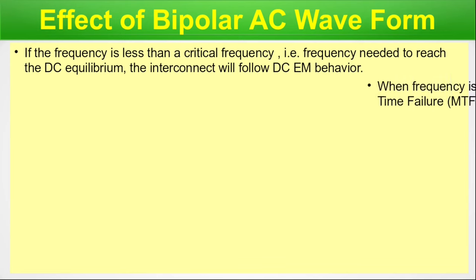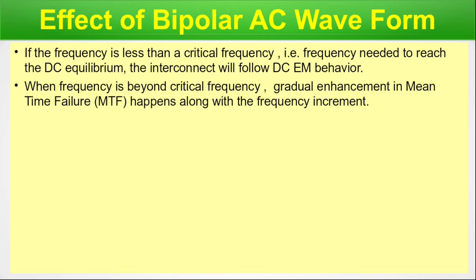When the frequency is beyond the critical frequency, that means the circuit operation frequency is much higher than the critical frequency, gradual enhancement in the mean time to failure happens along with the frequency increment. Now, what do you mean by the enhancement in the mean time to failure? That means the point of the failure goes away from the origin, that is x equal to 0 or time equal to 0 point. In the last episode, I have explained this mean time to failure with the infographics. There I have explained this. So that point of the MTF will go away further.